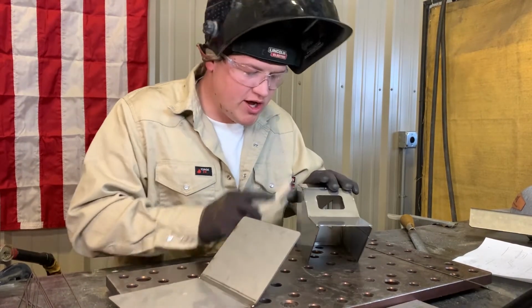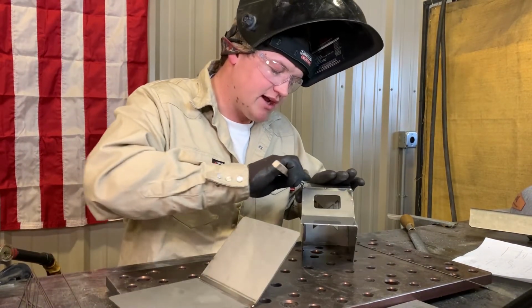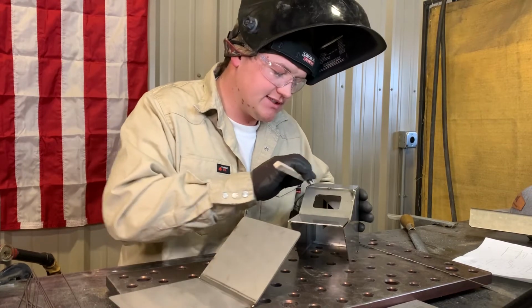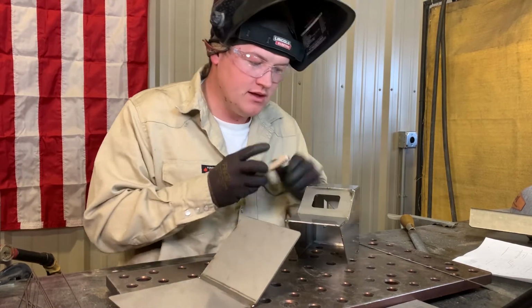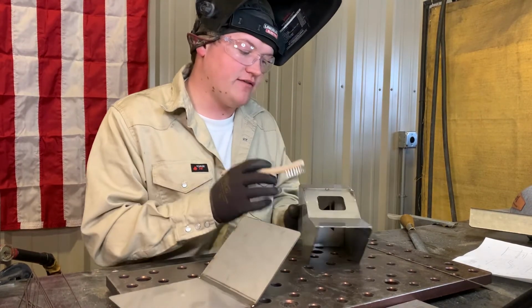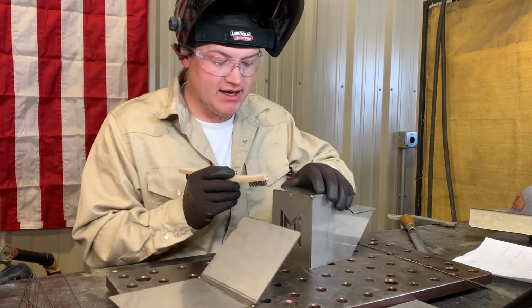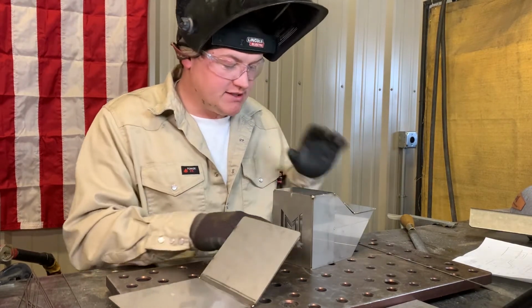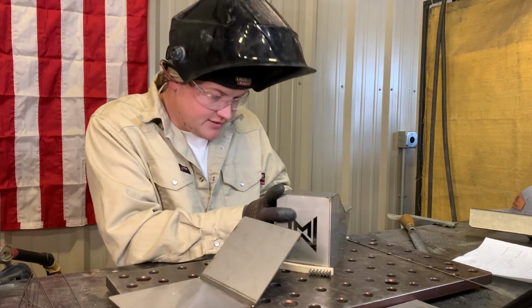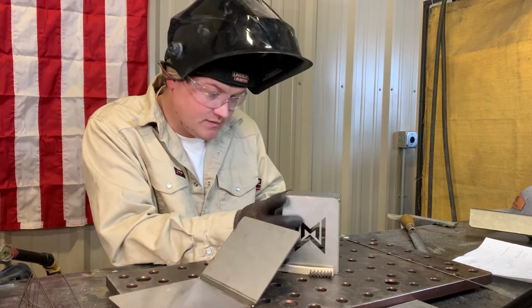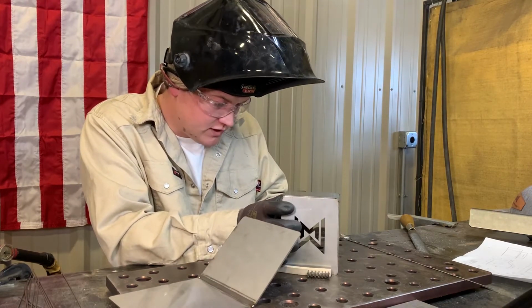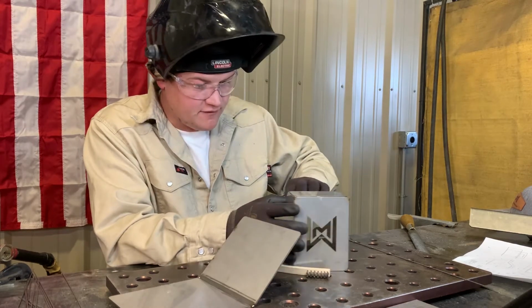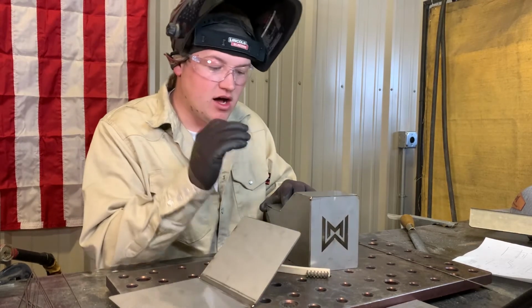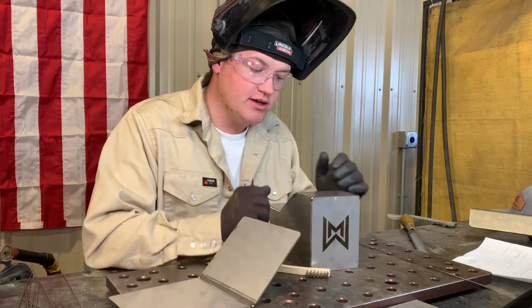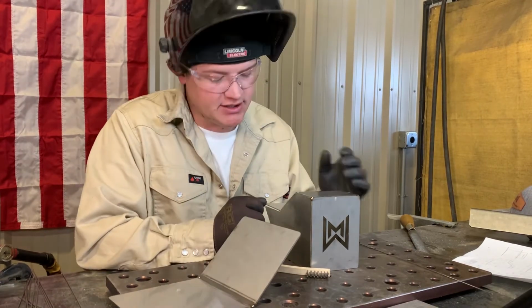And if you brush your tacks right after you tack them, while the stainless is still warm, it cleans that oxidized layer off way easier than if you let it cool down. It's something that happens metallurgically. I cannot tell you why. It's a little tip that I have found within the years. If you have a bad tack that gets oxidized quick, hurry, grab your brush, brush it off, and it'll polish off nice and clean.